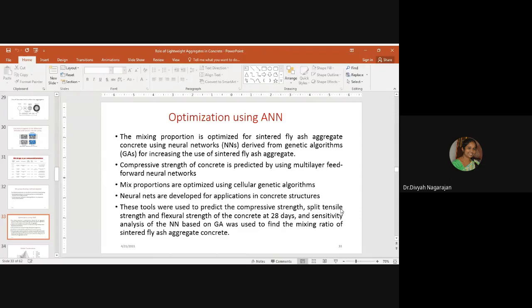First, the water cement ratio. The water cement ratio was fixed between 0.4 to 0.45. The dosage of the cement was varied between 300 kilogram per meter cube to 450 kilogram per meter cube as per IS codal provisions. Next, the mix proportioning was optimized for sintered fly ash aggregate concrete using neural network derived from genetic algorithms for use of sintered fly ash aggregate. I will not go in depth, but I'll say what I have done.